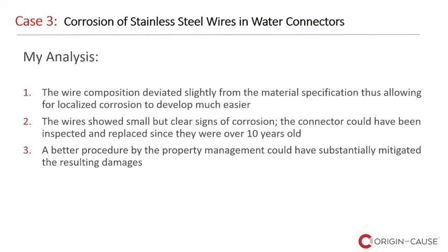And in my analysis, I was able to show that the wire composition slightly deviated from what the material specification was supposed to be, and that allowed for localized corrosion to develop much easier. It wasn't completely different from what it should have been, but it was enough that it would allow for corrosion to start. Also, the wires or the component, the connector, showed small but clear signs of corrosion. And in my opinion, this connector could have been inspected and replaced since it was over 10 years old.